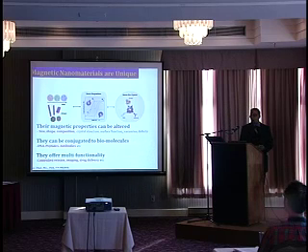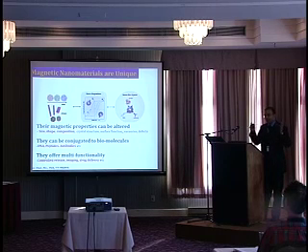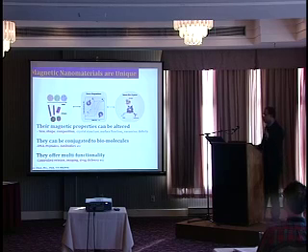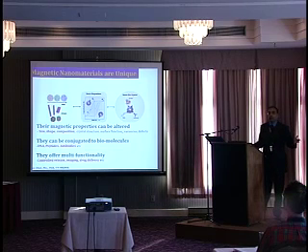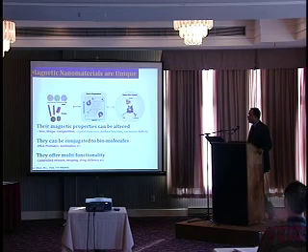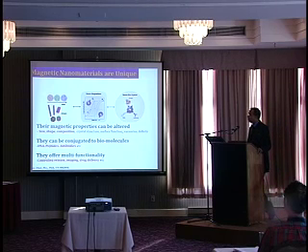Okay. So why are magnetic nanomaterials unique? They are unique, simple. I'm not going to take too much time. They're unique because of 3 very important reasons. The magnetic nano properties can be altered. In bulk magnetic materials, you have an opportunity to modify crystal structure, surface function, vacancies, defects, etc., in order to generate different magnetic materials with different magnetic properties. But when it comes to nano-sized magnetic materials, you have 3 additional components that give us an opportunity to change or alter the magnetic properties. These are size, shape, and of course the composition.